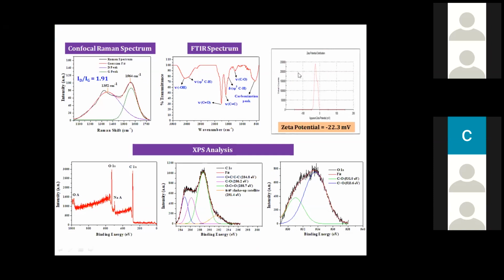Now, your surface charges can be analyzed by looking at DLS, dynamic light scattering, and measuring the zeta potential. Zeta potential gives you a measure of the extent of charges present on the material. Again, XPS analysis gives you the composition of this material - one can find out carbon, oxygen, nitrogen, all present as elements. That is how we take up this material and do a physical analysis, spectroscopic and physical analysis.